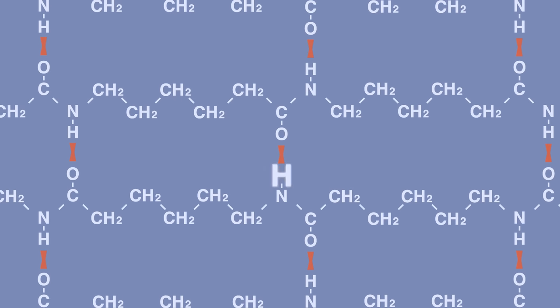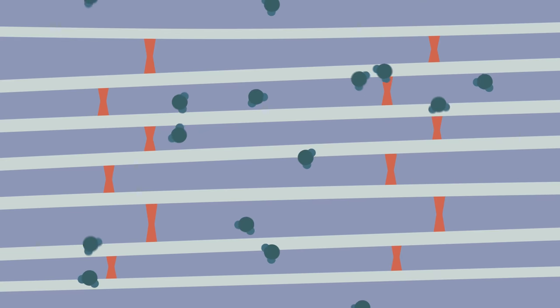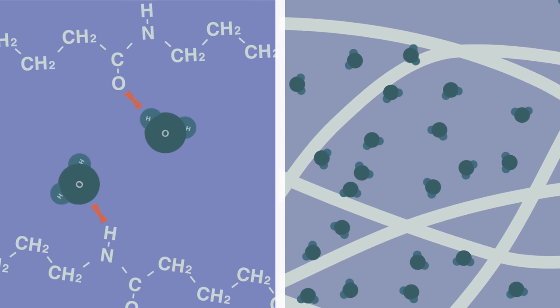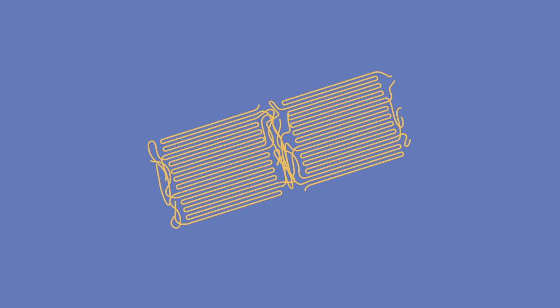Remember that hydrogen really likes oxygen? Guess what else has a lot of hydrogen and oxygen — that's right, water. Good news is that water cannot really penetrate into the crystalline parts of the fiber, because the chains there are already very tightly packed. However, the amorphous spaghetti parts have gaps, and that allows water to come in and bond to the chains. This bonding increases the distance between the chains and weakens the intermolecular attraction. So if force is applied when the fiber is wet, the spaghetti parts might stretch more than they are capable of recovering from, potentially damaging the entire structure. But all of that is in theory.